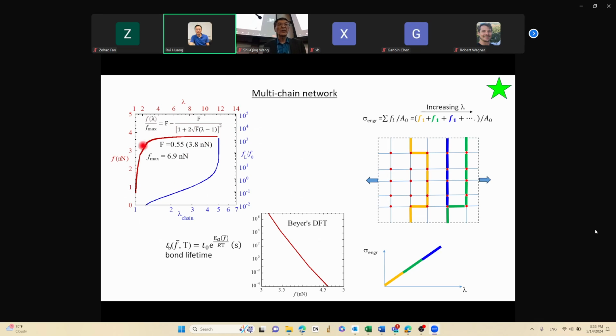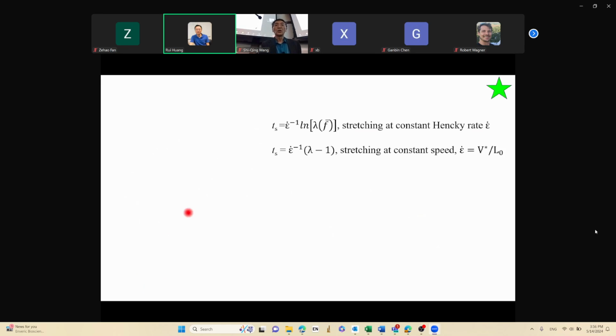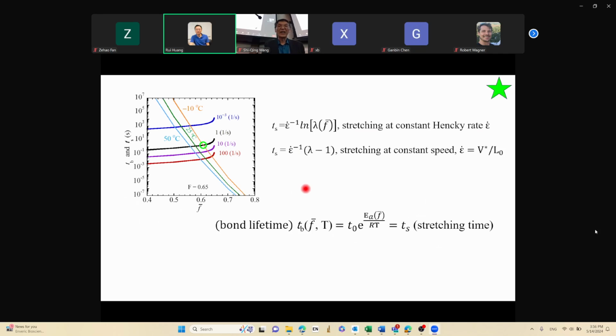And moreover, I focus on chain tension only in about the 4 nanonewton region, because that is the region, according to density functional theory, where the bond lifetime is in the relevant range, 1 millisecond versus a day or 2. So basically, depending on how you stretch, you have a stretching time. And my theory is that the stretching time is waiting for the bond to break. And you plot those two dependences with respect to tension amount. Graphically, I can find a point. That's the crossing point in green there. And then that's the point where I can find out the rest.